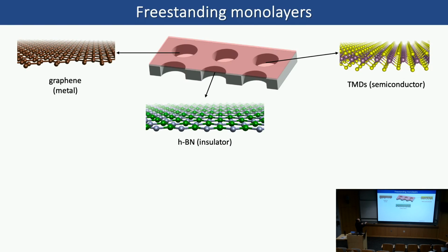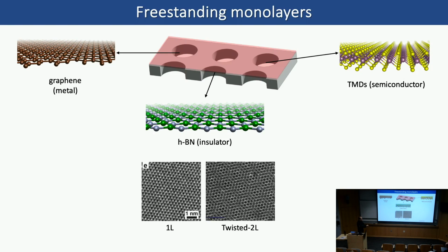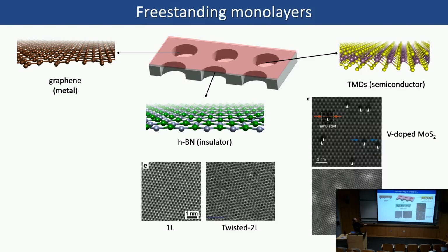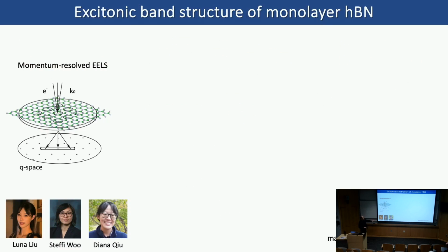But okay, so now we get all kinds of freestanding monolayers. We could have graphene, which I showed you how we could manipulate atoms. We could have hBN, which is an insulator, and all kinds of TMDs. These are the atomic images for hBN, 1 layer or twisted bilayer where there's a moire pattern. We can also grow pristine TMD, like in this case MoS2, or a doped MoS2. Or we could make these heterostructures, stack them, combine whatever way you want. Okay, so this is something that we're working on.